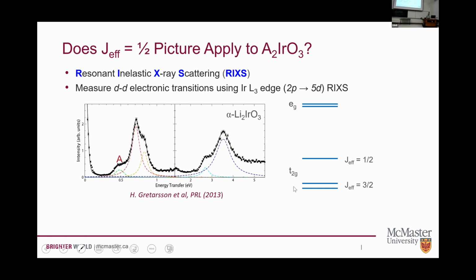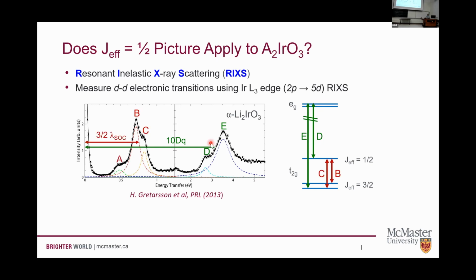So the first thing that we can do that's useful from this is to look at the electronic transitions, so looking at these orbital excitations, and we can assign these to an energy level scheme. Okay, so this is the scheme that we saw before from the effect of our crystal electric field and spin orbit coupling. And so we've got what we expect to be filled J effective 3/2 levels, a half filled J effective 1/2 level, and these empty eg levels. And so these different features that we see in our RIXS spectra correspond to these different transitions between these d levels. So what's important here is that the gap from the elastic line here to these features here tells us about the splitting between t2g and eg levels. It's about 3 electron volts.